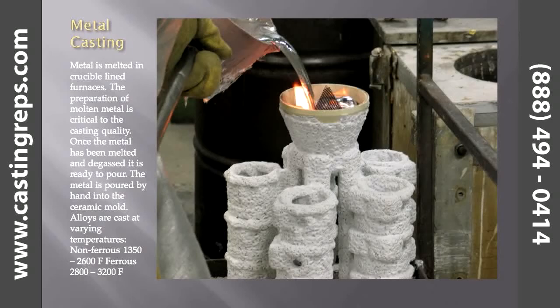Alloys are cast at varying temperatures. Non-ferrous, 1350 to 2600 degrees Fahrenheit. Ferrous, 2800 to 3200 degrees Fahrenheit.